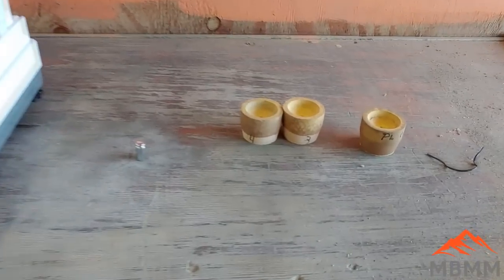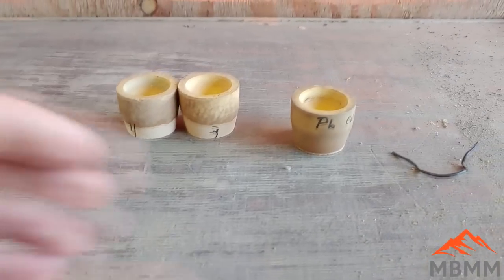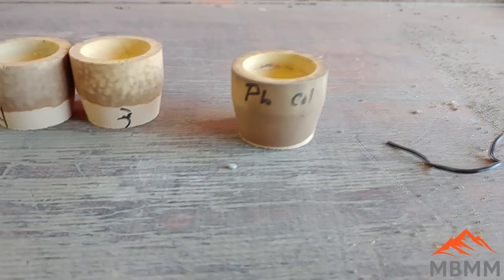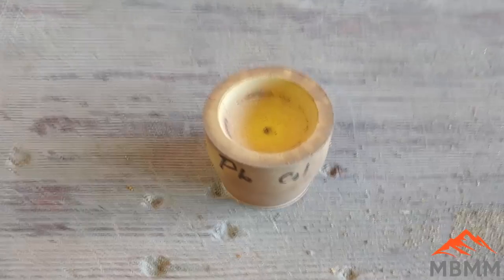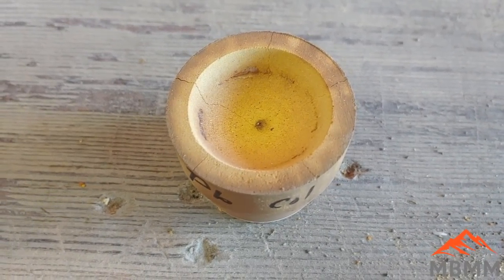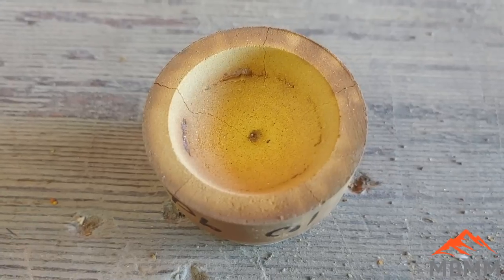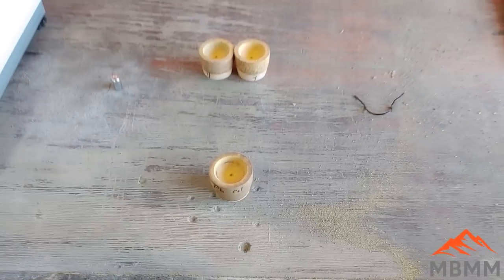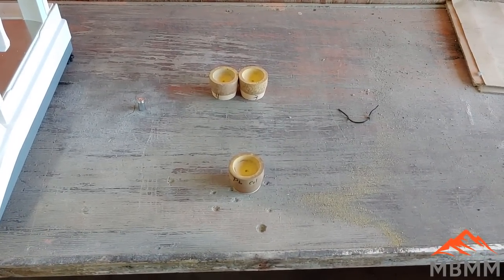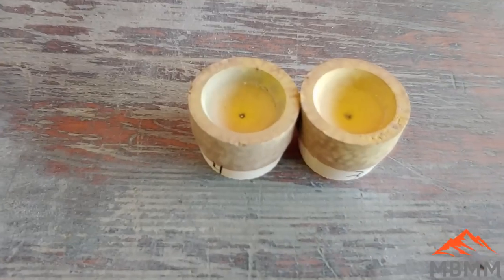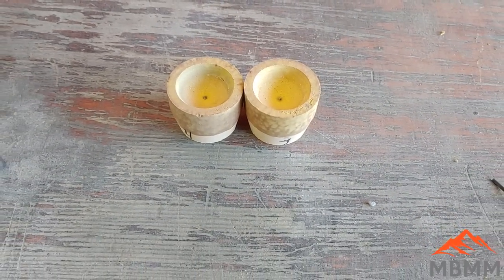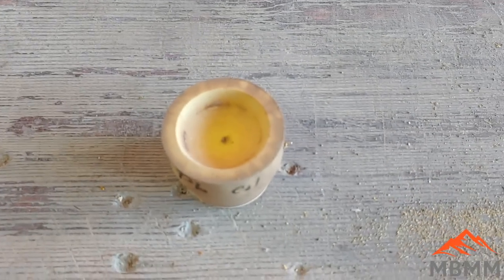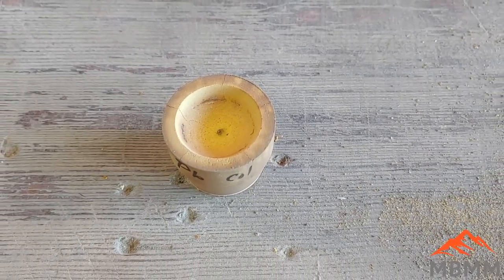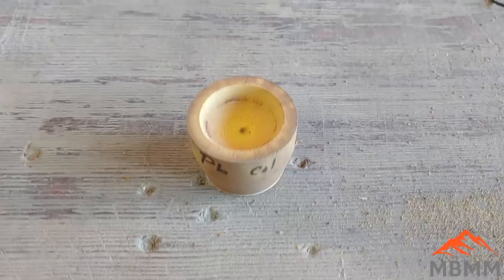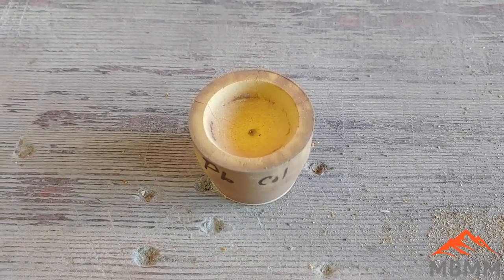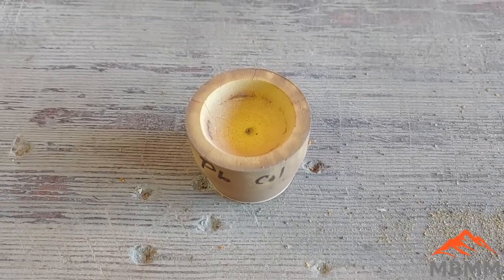And so we've got our number 3 and our number 4 here. But before we do that, we have to figure out how much silver is in our lead. And so I did a Cupel with 30 grams of lead, and there's the little bit of silver we got out of those. So this really doesn't matter when you're doing big smelts where you're getting multiple grams or even tenths of grams of stuff. But when you're doing these tailings samples or these other little tiny beads, you really got to figure out how much silver's in your collector metal so you can subtract that out so you don't get twice as much precious metal as you think you do. So let's get our lead collector bead weighed, and then we'll know how much to subtract off our number 3 and number 4 bead so we can get an accurate result.